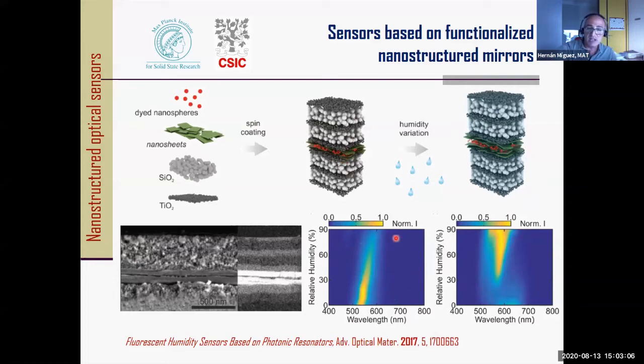And this is the experimental result. Basically, when you expose to increasing humidity a system like that, you start with a very intense emission in the green that disappears above a certain level of humidity. Or you can make the opposite design and start with a material that doesn't show any luminescence for low humidity, and above a certain humidity starts emitting. So this is just a proof of concept of how you can combine many different nanomaterials, and this is typical of nanotechnology as well, combining many different types of materials in complex structures, to obtain a sensor, a photonic sensor for humidity, for changing humidity.